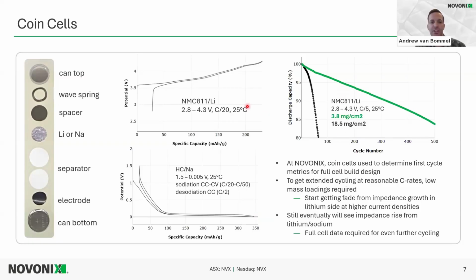So we typically use coin cells to determine first cycle metrics for a full cell build design, but often we want to get extended cycling from coin cells. But in that case, low mass loadings are required. So here I have a graph of an NMC 811 lithium coin cell cycling at C/5, 25 degrees, and with a normal mass loading. So this would be a good, industrially applicable mass loading of 18.5 milligrams per centimeter squared. We get rapid fade with cycle number.